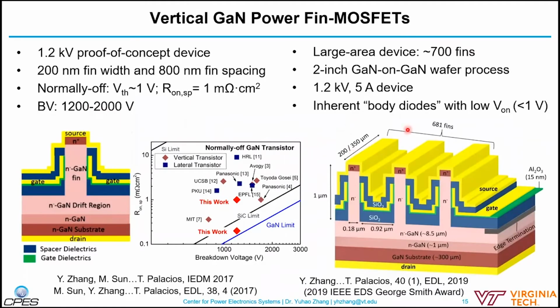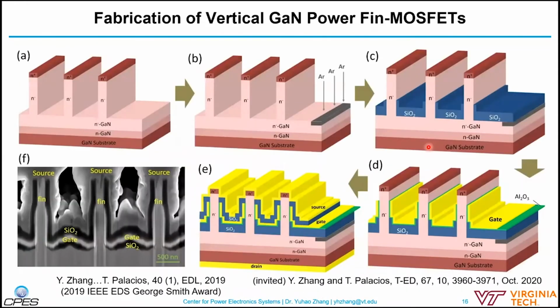And then we spent quite some time, close to 2 years, trying to fabricate these devices on 2-inch GaN wafers. It's a very painful process to fabricate the wafer level devices using the university fab. But finally, we were able to make some 5 amp, 1.2 kV devices, and each device has about 700 fins and can support an on-state current of about 5 amps. And this shows essentially our fabrication process.